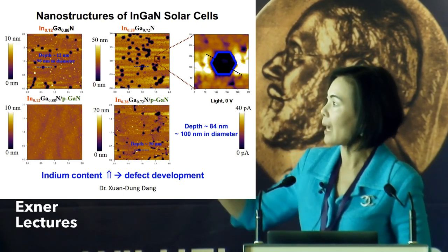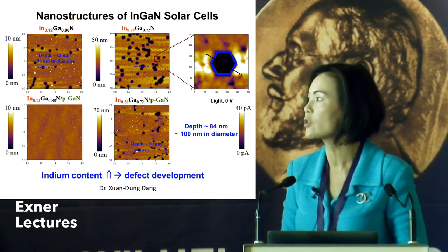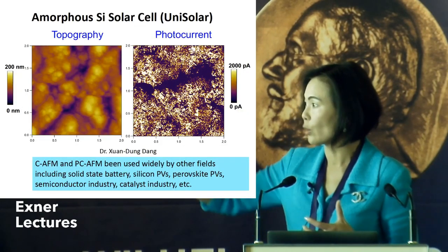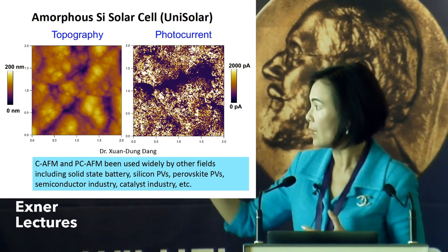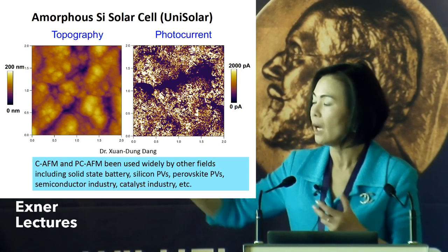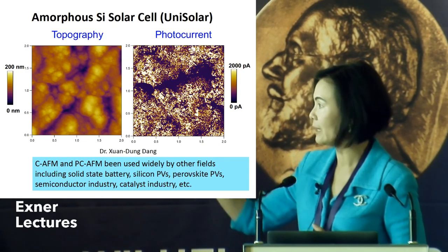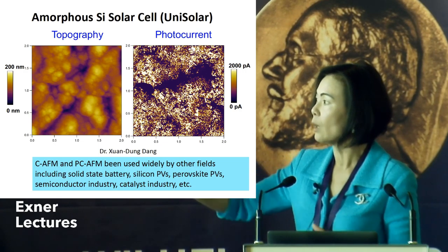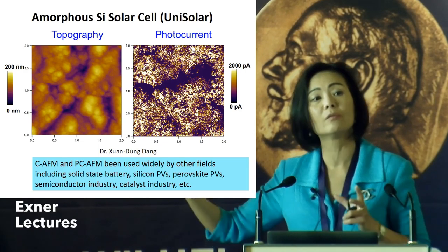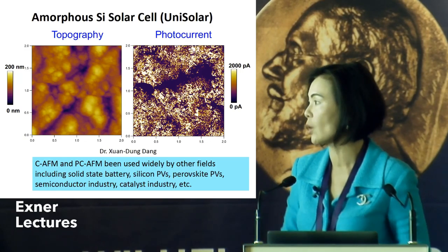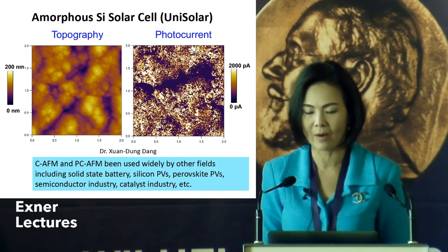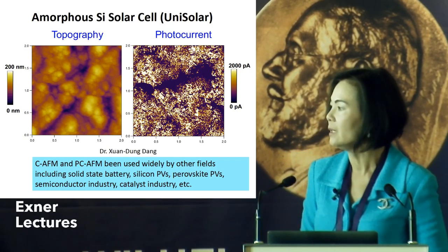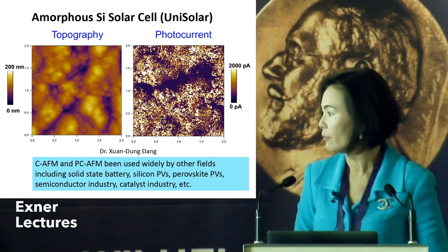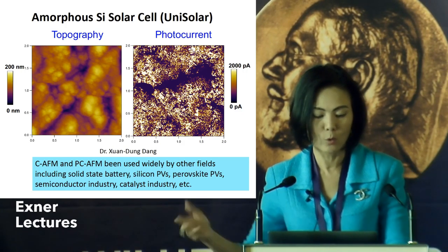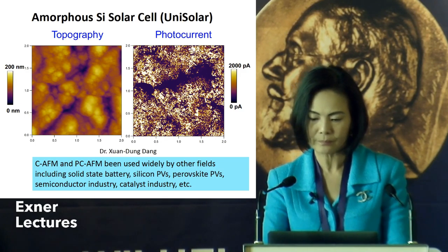And then we also applied the technique to help the Unisolar cell company characterize silicon solar cells. And we could see they have different growth conditions. And we were able to see that a weak growth condition leads to better, higher photocurrent, and also correlate that to device performance. And you can see here there are a number of fields that apply the tool to that.